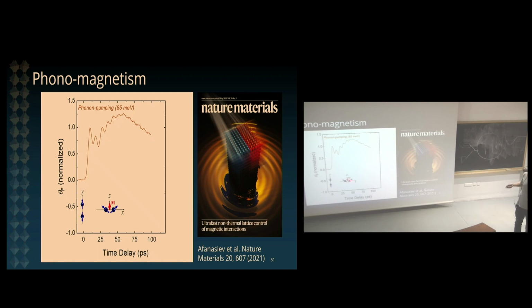So this is telling us directly that we are moving from this antiferromagnetic state to this non-collinear antiferromagnetic state with a net magnetization. The transition from one state to the next occurs within the first cycle of the spin precession. It's a very fast transition, within a few picoseconds. You can contrast this with an excitation of the electronic degrees of freedom. So this goes back to the question: are you heating the system or not?